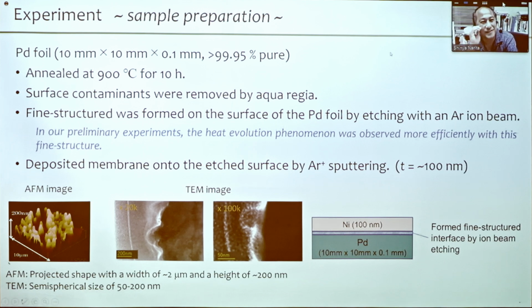Yes, starting with the sample preparation. We use the palladium foil with the size of 10 millimeter square and the thickness of 0.1 millimeter with the purity of above 99.95%. And at first we annealed the sample at 900 degrees Celsius for 10 hours. Then we removed the surface contaminants by the aqua regia. And fine structure was formed on the surface of the palladium foil by etching with an argon ion beam. As I showed in the previous slides, fine structure of the sample is supposed to be one of the important conditions for inducing the phenomena. That is why we form the fine structure on the surface.